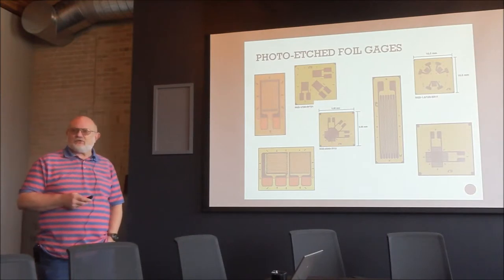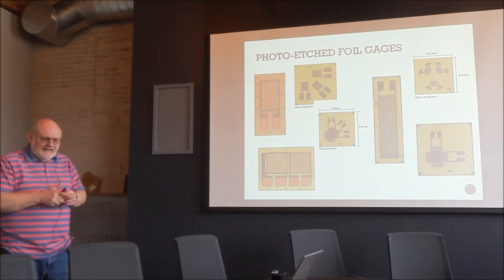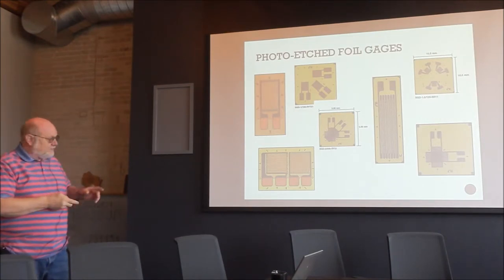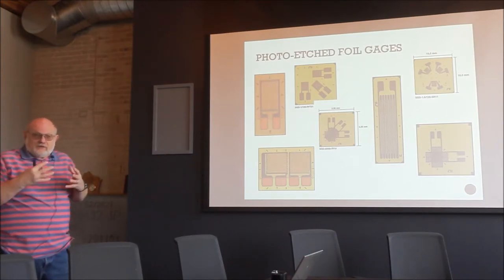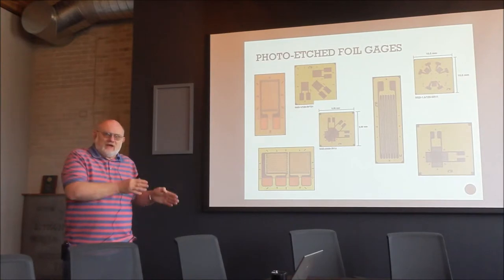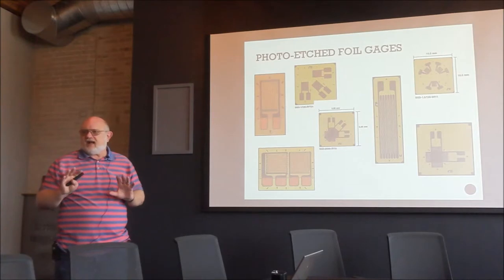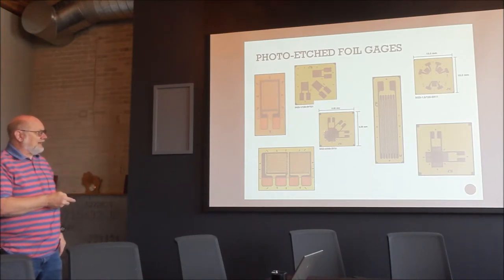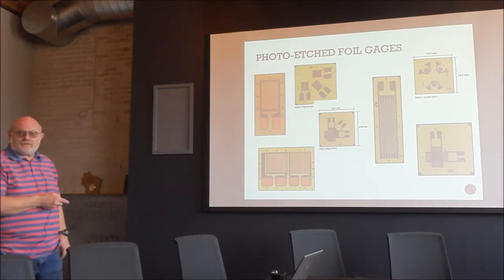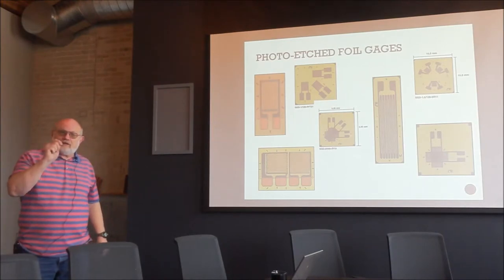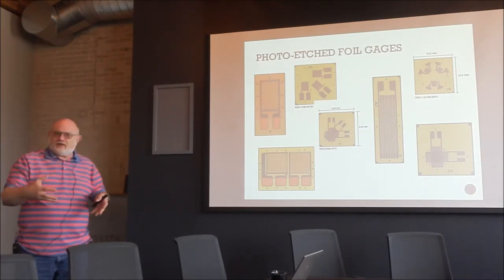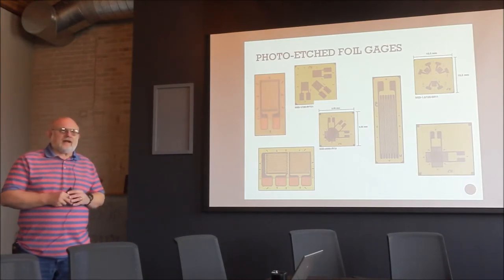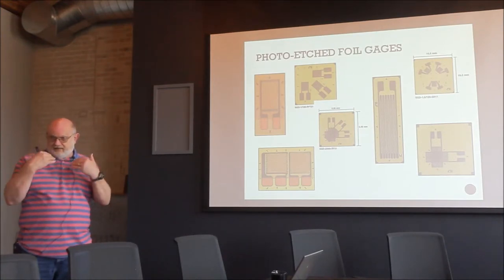The hole-drilling technique relieves localized residual stress, which is then measured. You glue the rosette down, put an end mill in a hand drill — everything rigid below — and drive it down through the array. The critical challenge is not inducing additional stress during cutting. A more extreme version used even smaller gauges with elements a 64th of an inch, mounted and trepanned around with a dental drill and diamond bur under a microscope — a very artsy, technique-dependent process.